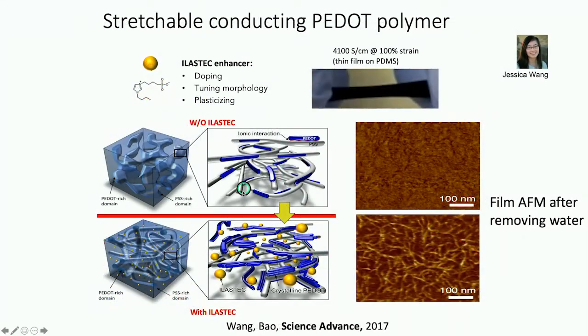So this is one version of such material that we found that using ionic liquid incorporated into the conducting polymer solution, then it can induce these kinds of fiber formation to give us the conducting pathway that's needed to get very, very high conductivity. But at the same time, the material remains highly stretchable, even up to 100% strain, and the conductivity is among the highest known for those of conducting polymer, several thousand Siemens per centimeter. And this is one of the first such conductive polymer that has both high conductivity and also high strain tolerance. But of course, the ionic liquid may be potentially toxic to biological system.